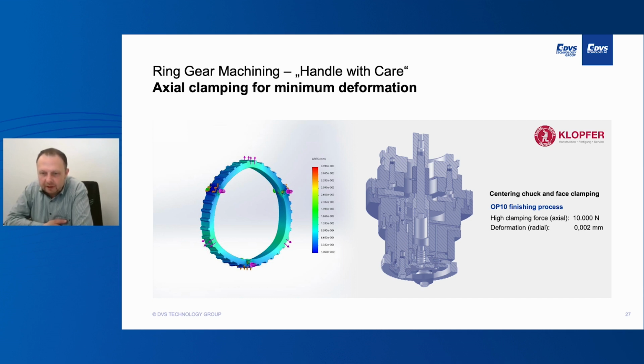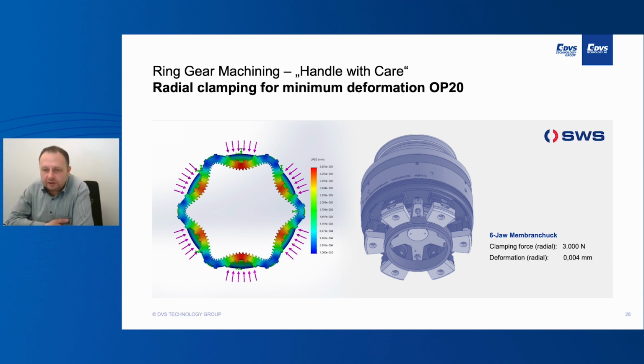One solution shown here is working with a slight centering so that we avoid any deformation in the circle, and a face clamping with 10,000 Newton. This avoids the radial deformation, less than 2 microns. Another solution could be a 6-jaw membrane chuck, and with this, less clamping force is necessary. We're working with 3,000 Newton, and with the 6 jaws, it's possible to have more or less equal pressure over the 360 degrees, so that we don't have much deformation. We're talking about 4 microns in that case.